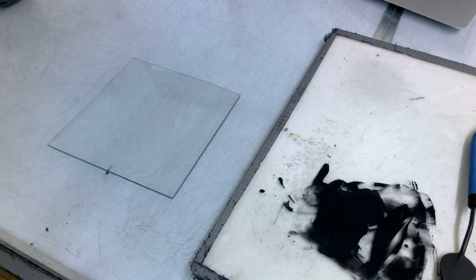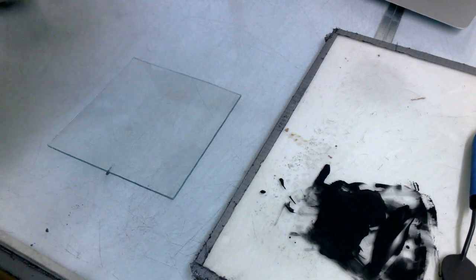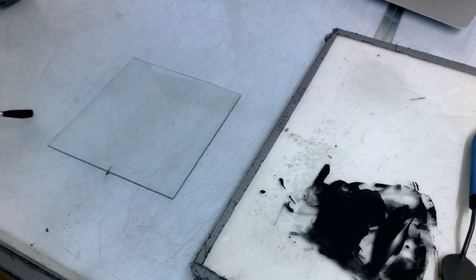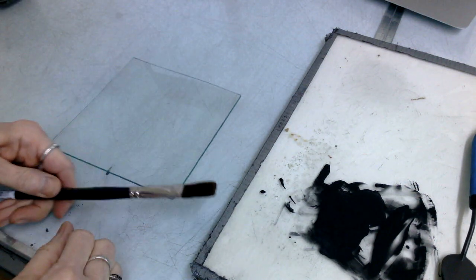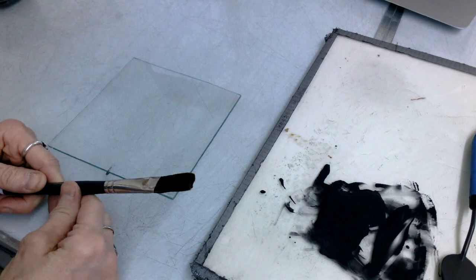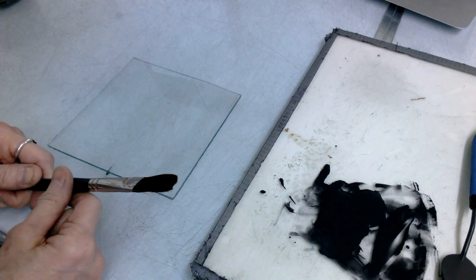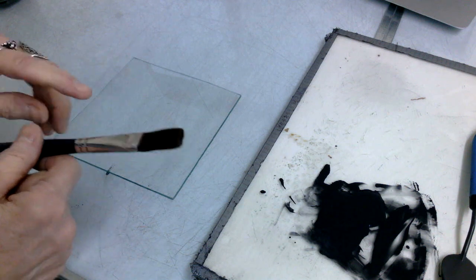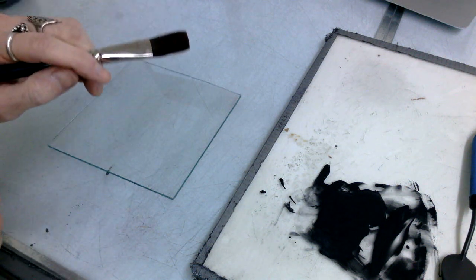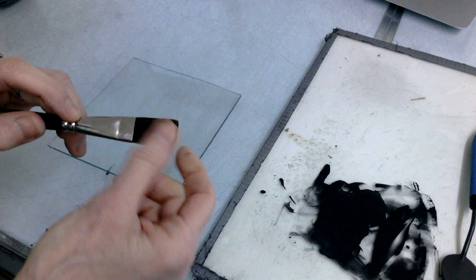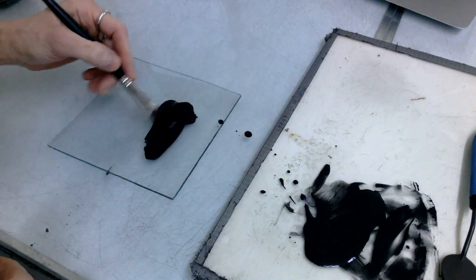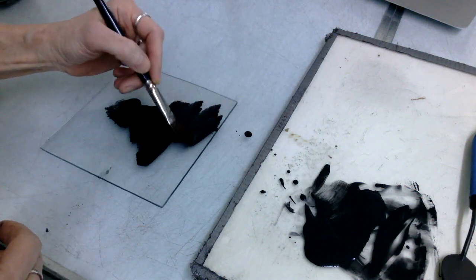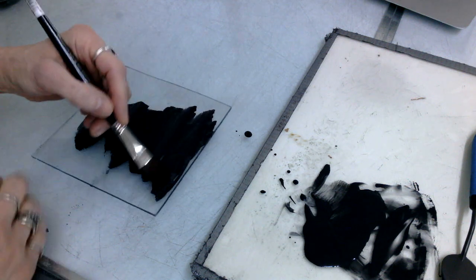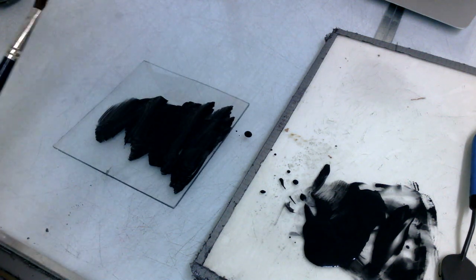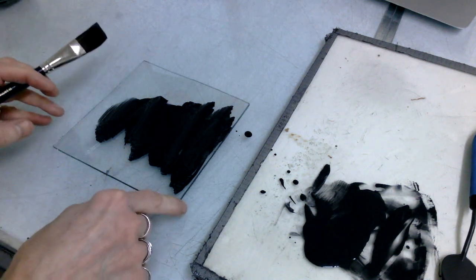To get darker, richer tones or blacks, another layer must be painted and fired, sometimes multiple layers and multiple firings. There are ways to paint on glass without multiple firings in the kiln, but for now, suffice it to say that if you are thinning your paint with water, and you try to paint another layer on top of your previous water mat, you will simply wash away the previous mat and make a mess. So you must fire in between.